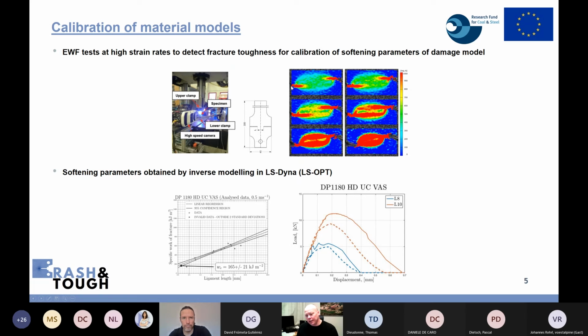In the image to the right, you can see how the strain rate develops during the test. You see you have a fully plastic zone in the ligament, which is important for this procedure to work. As you can see, you have strain rates of the order of thousands. So what you do in the next step is run inverse modeling using LS-DYNA, actually LS-OPT, to calibrate the softening parameters within the GISSMO model.